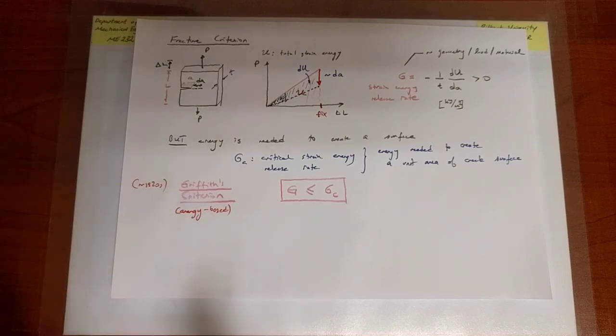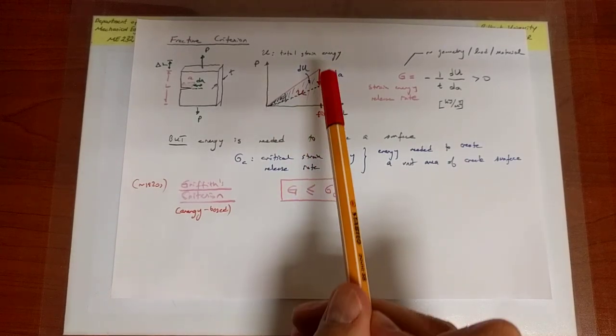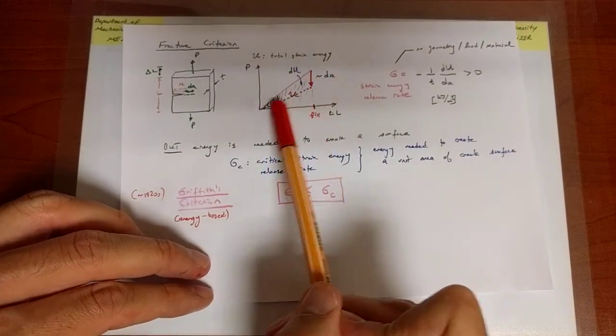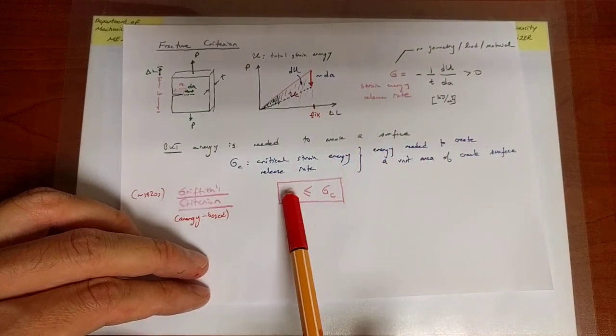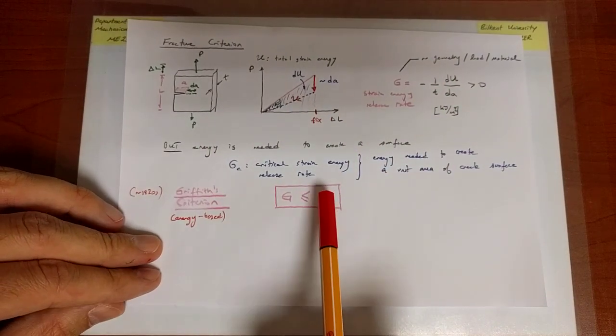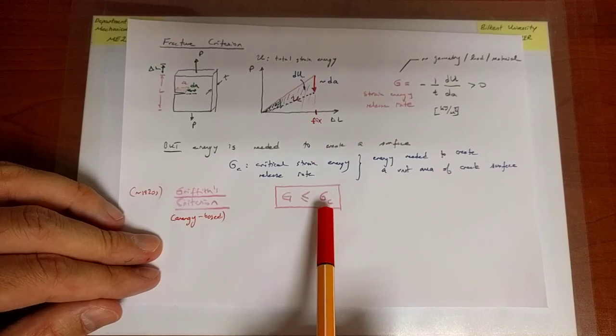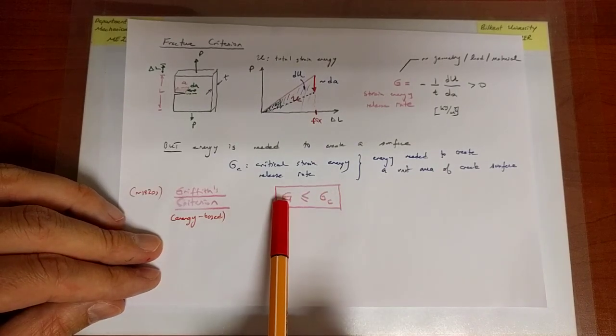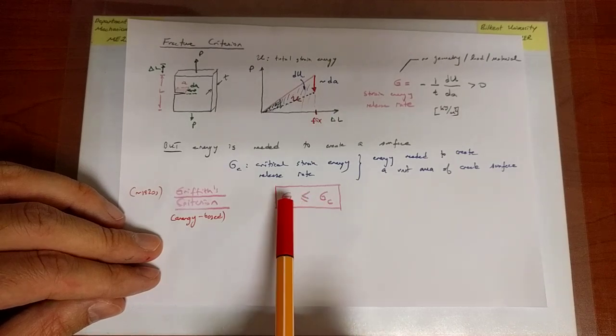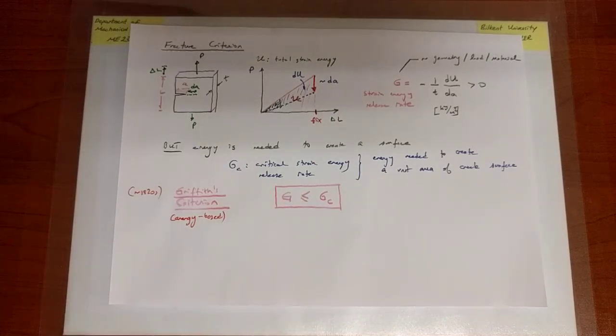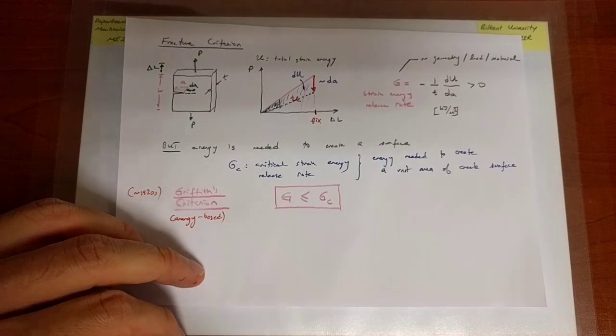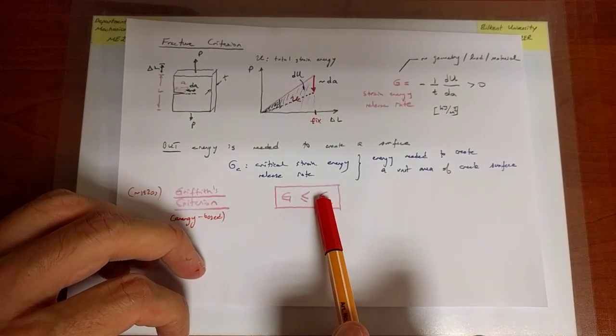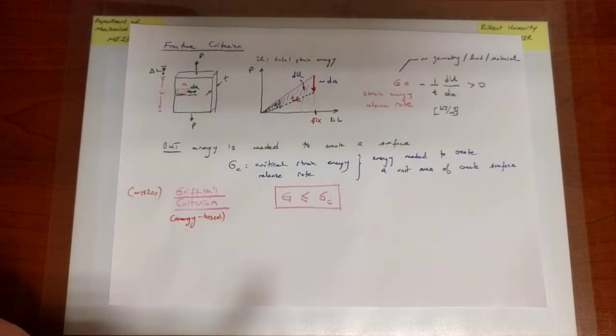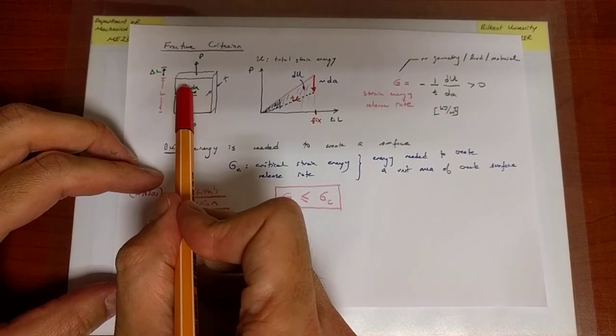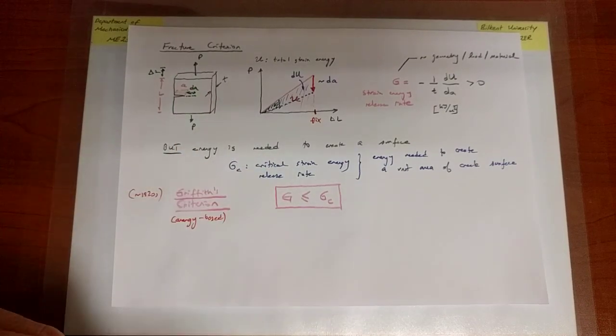Now, the reason I said my process was a little bit different is because I have assumed that all the energy that is being released from the system is going into the creation of new surfaces. So there's a certain energy that is required to create the surfaces, and the system releases some amount G, and I'm setting G equals GC, and that's when failure occurs. So what I'm saying is all the energy that is released from the system is going into the creation of the surfaces. But in reality, perhaps in my experiment, the tape was deforming plastically, or perhaps in this case, this is a metal, there's significant plastic deformation.